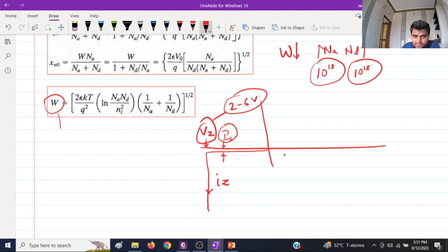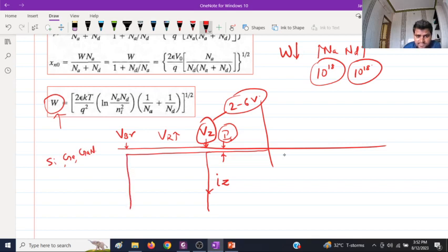If any of these conditions is not met, that is, if W is not very small, then this will not happen and the Zener breakdown will not occur. If you keep on increasing the reverse voltage, it will continue up to the normal breakdown of the material, which depends on whether it is silicon, germanium or gallium nitride. Large band gap materials have high breakdown voltage, but for silicon it generally varies around 50 to 100 volts.